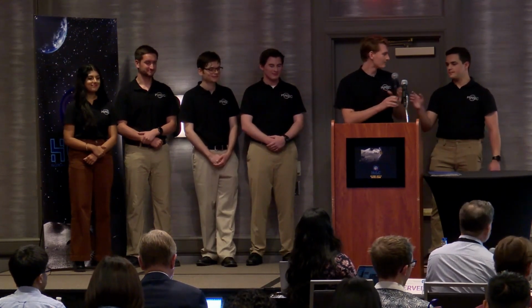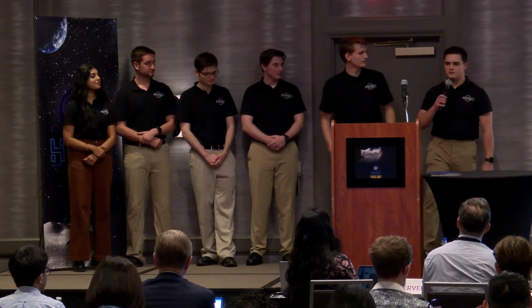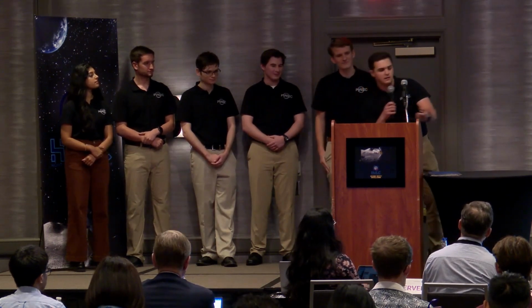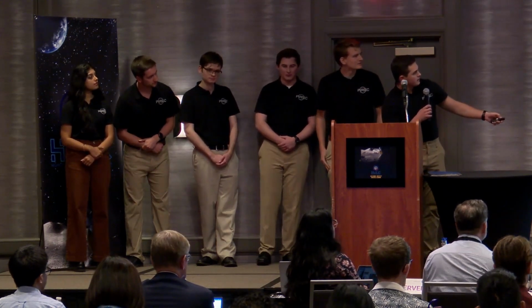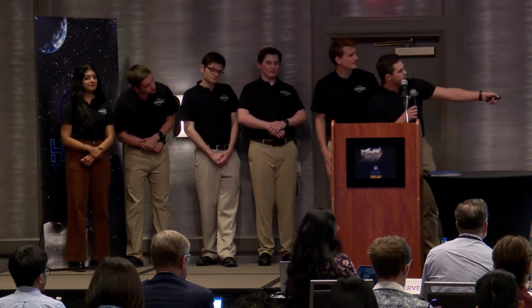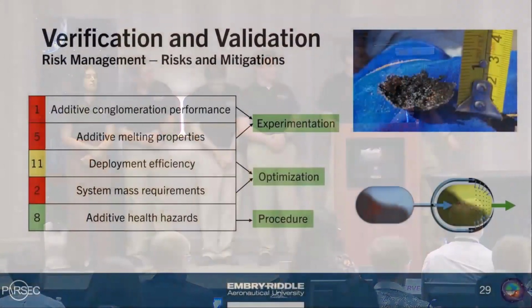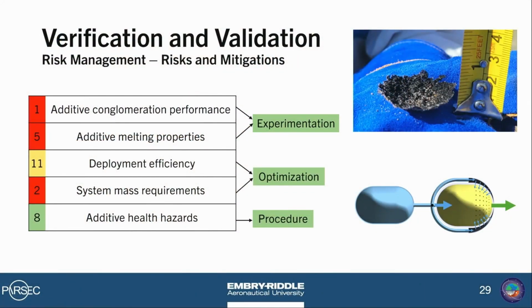Okay, thank you. If I could add on to that question really quickly, while we were testing, we had a sample, I think it's over here. Yeah, if you can see up here, we had a sample that when we were blowing the torch, it was only a few inches away from the surface of the sand. So it was actually causing a crater. But while the crater was forming, we did get that landing pad as a result. So it may be possible to still conglomerate the surface while the plume is interacting close.